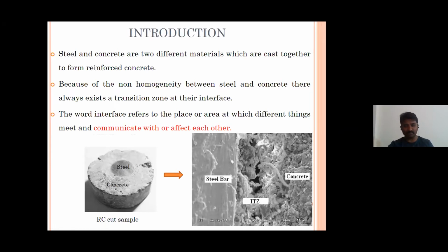What happens when there is more water and few cement particles? Obviously, there is a higher water cement ratio. And we know what happens with a higher water cement ratio: there will be voids. As the water cement ratio increases, the voids in our concrete increase, and the same phenomenon happens here also. The cement particles move away, there will be more water and fewer cement particles, and once the cement dries, there will be a porous region like this.